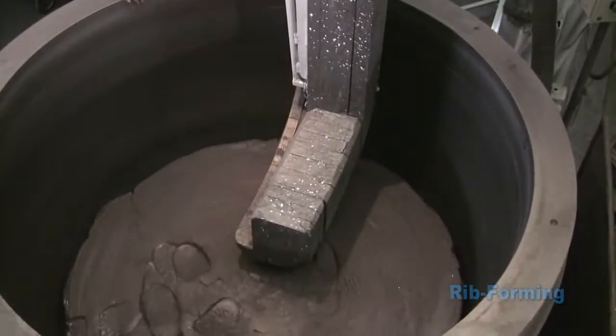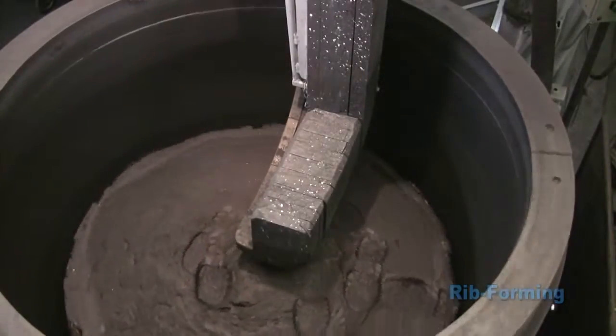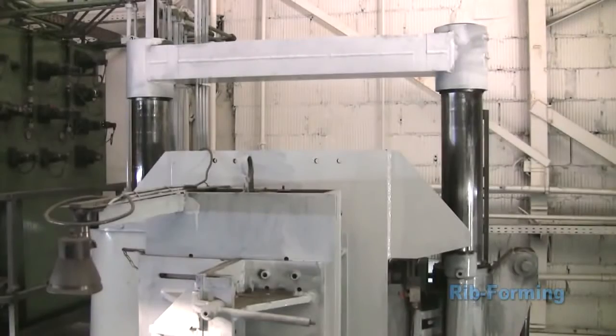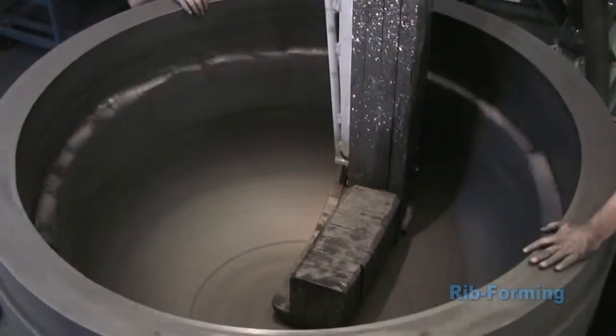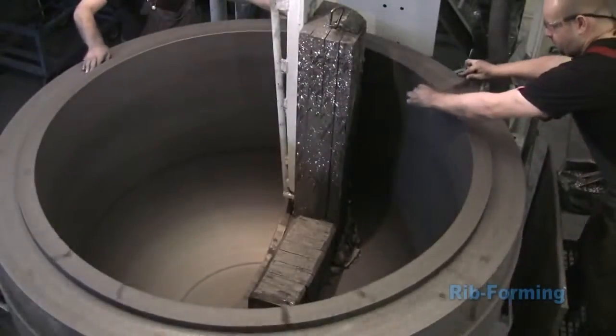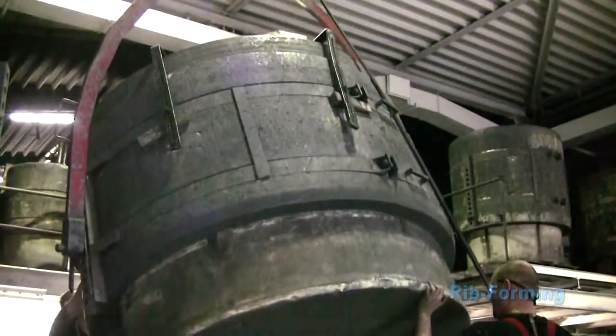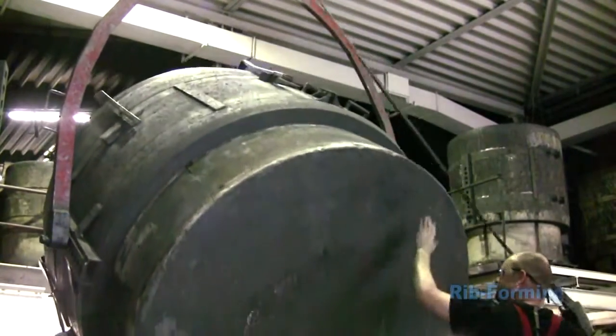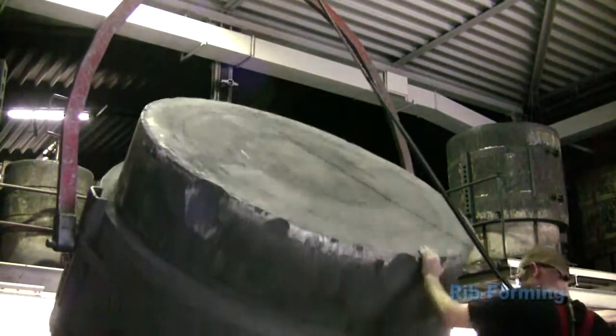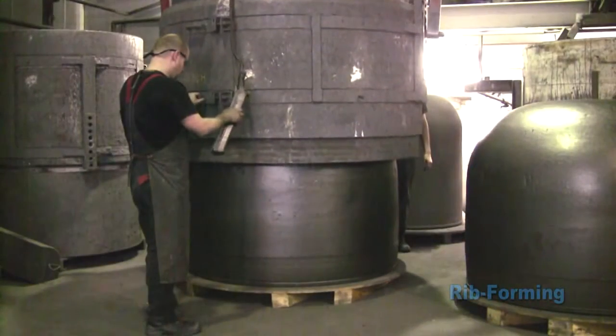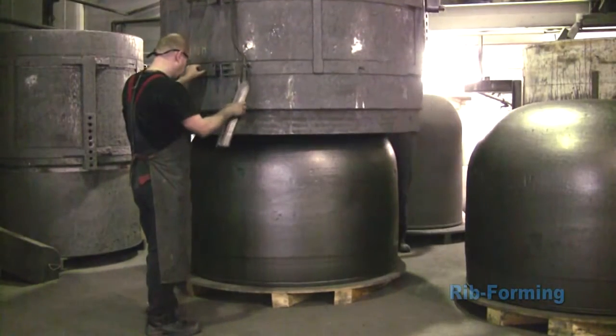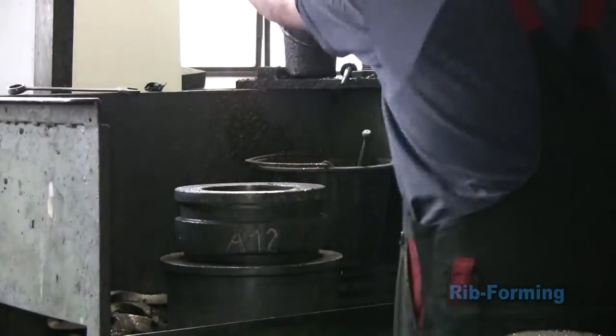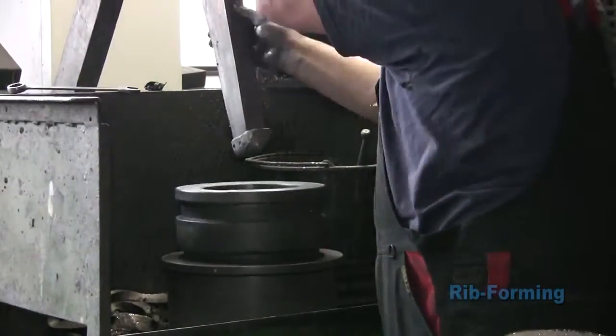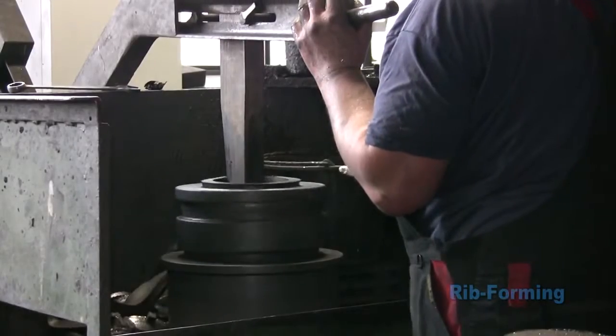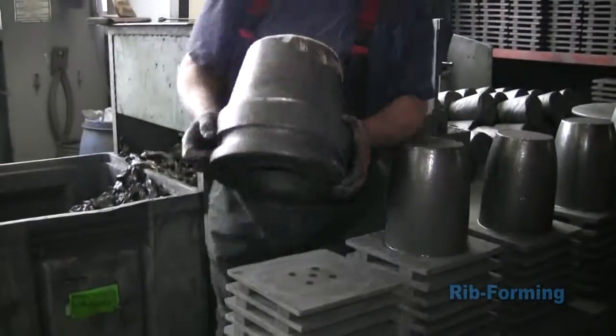As the turntable holding the crucible begins to rotate, a hydraulic ram presses the rib into the clay graphite material in the bottom of the mold. It exerts pressure up to 5 metric tons. After the mold is removed and flipped, the crucible is carefully removed. This automated process produces a crucible with a far more uniform shape and density than is possible with hand-forming techniques. Rib-forming small crucibles uses a manual system taking advantage of mechanical leverage to apply the pressure needed to form the crucible in the rotating mold.